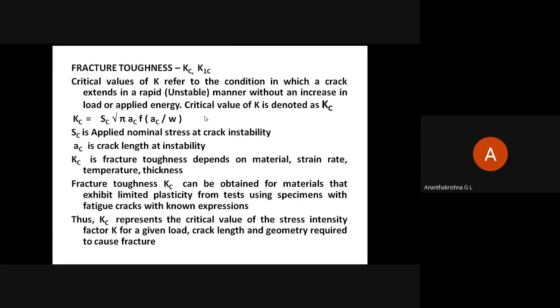That is essentially what happens beyond your ultimate strength in the stress strain diagram, if you remember. Beyond ultimate stress, even without application of load, the deformation keeps going till fracture occurs. So that value of K is called the critical value of K, essentially given by the critical stress, or stress at instability, and the crack length at instability is a_C. So K_C equals S into root pi a_C into F of a_C by W.